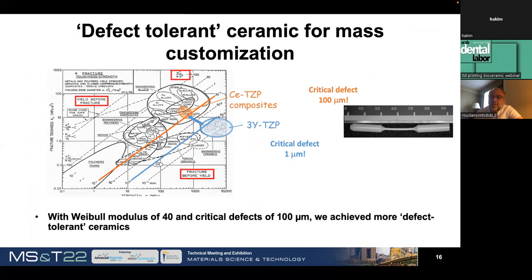Here on this diagram, you can see 3 yttria zirconia in the blue area, and the orange one is the new ceria-doped zirconia composite, which allows a critical defect, tested by Vickers method, of 100 microns instead of only 1 micron for the traditionally used zirconia. This picture on the left gives you the understanding of what I'm speaking about. It means that in some way you can even bend this ceramic material a little bit, which is really new for this field. The critical defect is just 100 times more than the critical defect of the traditionally used material.